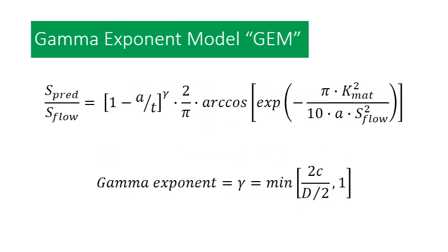So those of you that are watching the video series might be familiar with my Gamma Exponent model here. You'll see that it's mathematically in a very similar form to the original log secant model that was put out in the 1970s by the NG18 committee at the Battelle Institute in Columbus, Ohio. The key thing with this GEM model, though, is that it's been mathematically derived based on depth of a surface crack, as opposed to the original log secant model, which was originally derived based on length for through-wall cracks. So there are a couple of fundamental differences that I've put in to hopefully improve model agreement to actual real burst pressure data.